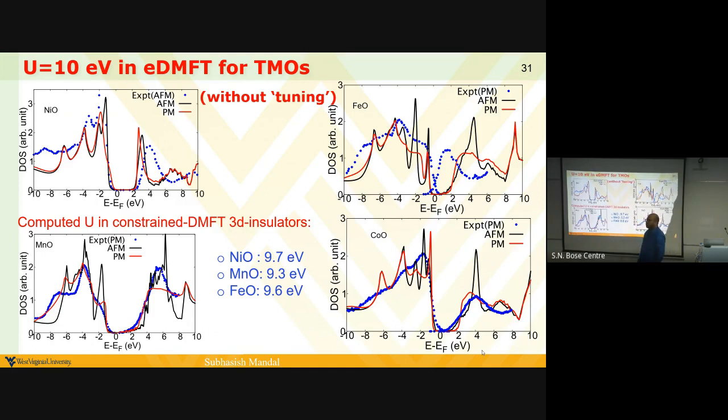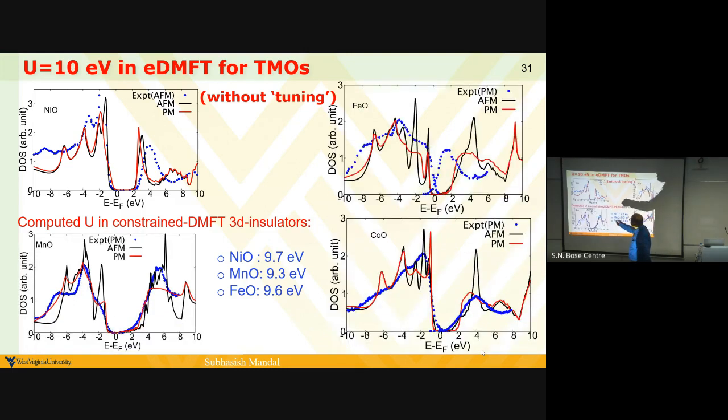But they will get correlated because there is a covalence. Right, but the hybridization is going to take care of that. Because I'm using a large window, the hybridization will take care of it. That's why we get a very good match, even for the oxygen in the hybridized state. Look at it with the experiment. Wonderfully matched, because of the large window. Yes, that is kind of the trick here.